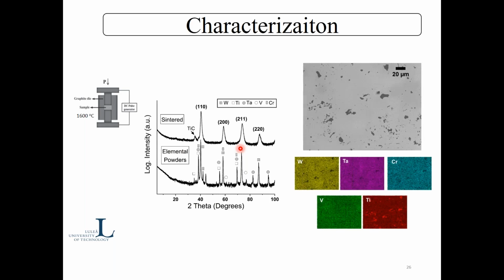And this is the microstructure, and you can see the microstructure has a contrast, and we get some titanium carbide particles, but the rest is quite homogeneous. And you can see the elements like tungsten, tantalum, chromium, vanadium, and titanium are homogeneously distributed in the solid solution.